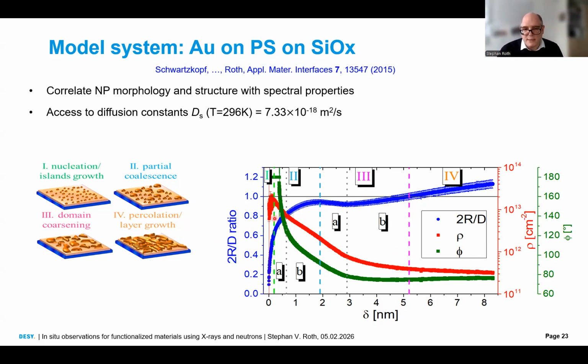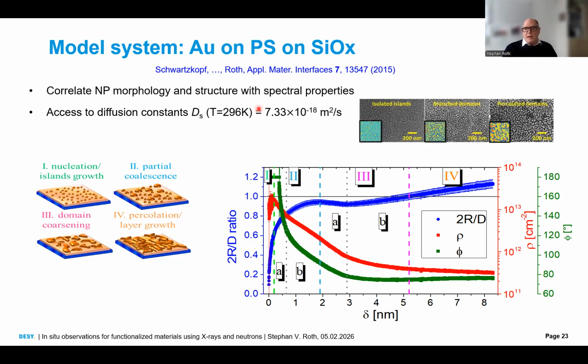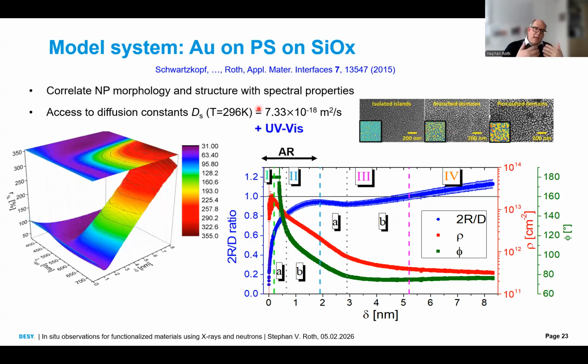We can also give you the cluster density in full detail, and we can give you the cluster shape. So this is the phi angle, meaning phi equals 180 is a full sphere, 90 is a hemisphere, and below 90 is one of these capped spheres. So we can follow really the size and the shape of the clusters in all detail. We can also deduce by our measurements diffusion coefficients of gold on a surface, which is valuable input for molecular dynamics. We can, of course, compare to SEM images, which fits very well. And we can compare to optical measurements.